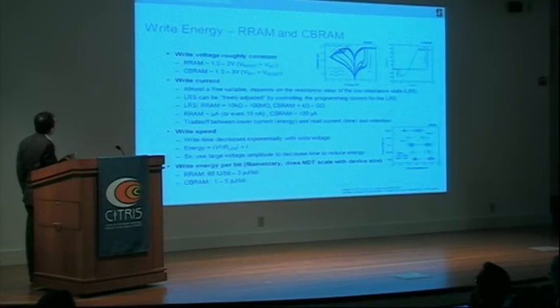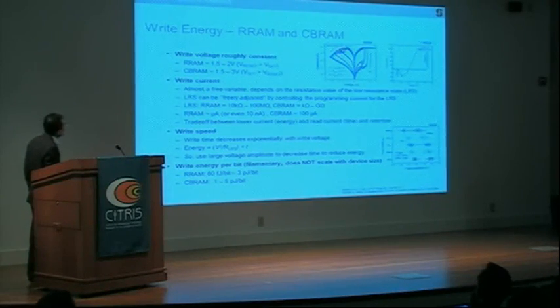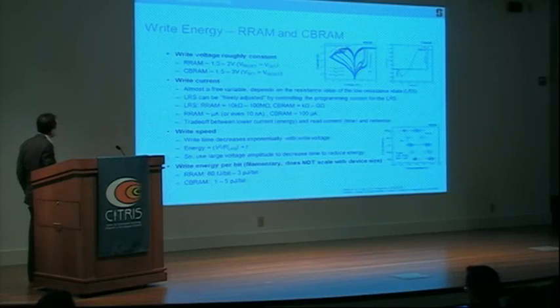Let's start with the write voltage again. The write voltage for RRAM is about 1.5 to 2 volts. So this is RRAM kind of IV curves. This is a CBRAM IV curve. You can see it's about 1 to 2 volts. The CBRAM is about 1.5 to 3 volts.